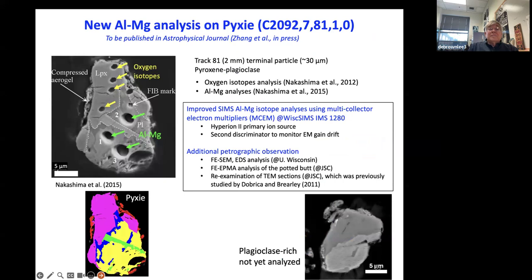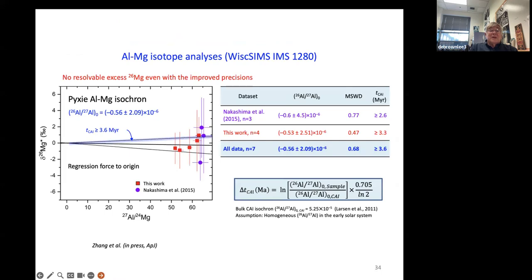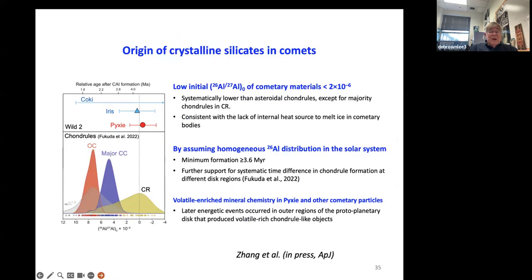The latest data has been done by Ming Zhang on the little sample called Pyxie, and it's a 30 micron particle. It's very interesting, the best results so far. The lower right-hand particle is a new particle that we just recently found. It's plagioclase-rich, and it will also provide more interesting data on aluminum-26. But anyway, this is the best data we have: no resolvable excess, even with improved precision on that grain.